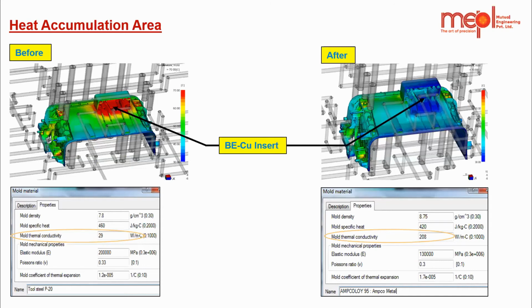As you can see, this part is very complicated, and the cooling is also very challenging. So we could not do the cooling as needed. As you can see, the red area is where heat dissipation could not happen. The material we used is P20, which has very low mold thermal conductivity, so heat dissipation is also very low.